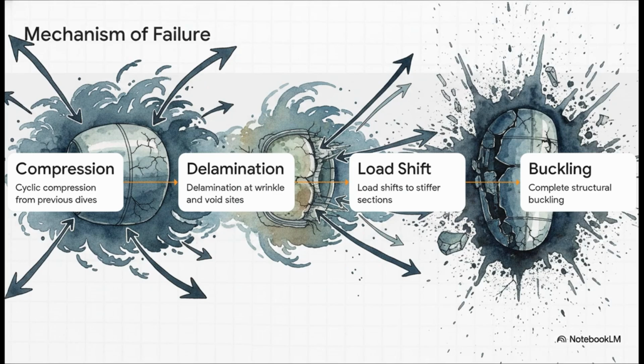So when we put all of this forensic evidence together, here's the 4-step mechanism of failure. Step 1, cyclic compression. Every previous dive subjected that hull to crushing pressure and then released it. Step 2, this cycle caused those microscopic wrinkles and massive adhesive voids to delaminate. Step 3, as the damaged areas became soft and peeled apart, the crushing load of the entire ocean was aggressively shifted onto the remaining intact, stiffer sections of the hull. And finally, Step 4, those remaining sections simply couldn't bear the millions of pounds of force all on their own. The result was instant, complete structural buckling and a catastrophic implosion.